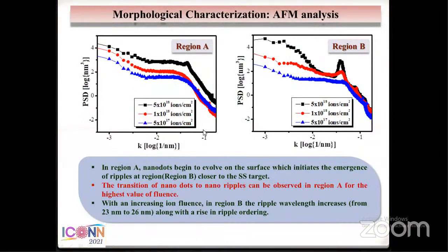This is the PSD diagram, that is the power spectral density function extracted from the AFM images, and this is for the region A and region B. And here we observe that in region A, a small peak is observed for the highest value of fluence, which indicates the emergence of ripple on the surface that we have also seen from the AFM images. And also in region B, it is observed that the peak of the power spectral density function becomes more pronounced, which indicates a higher value of ripple periodicity and ripple ordering.